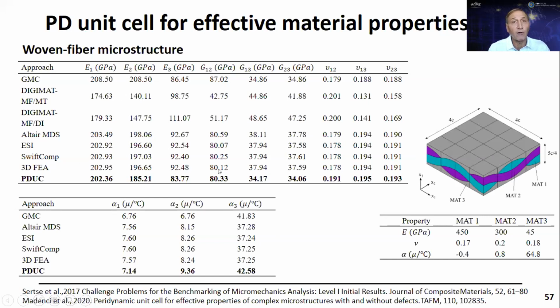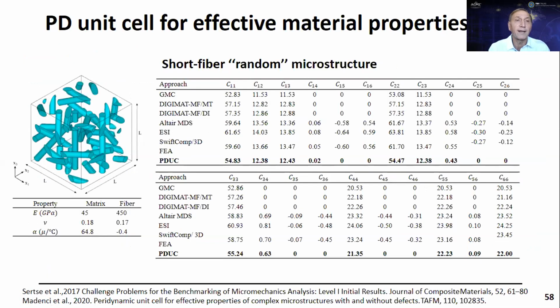We also applied our homogenization method to determine material properties in different directions. Very nicely captures what other methods also capture. What's important here is that we can put voids, defects, cracks in it. And I'm not going to show you here, but that's sort of what we've done. That was the exciting part of it. And also another complicated model they considered, they have these short fibers in the microstructure. Again, we modeled this with Peridynamics and it very nicely captures the material properties in different directions.